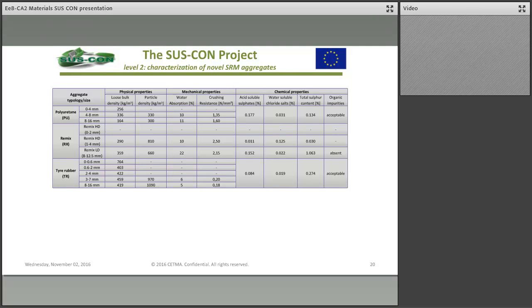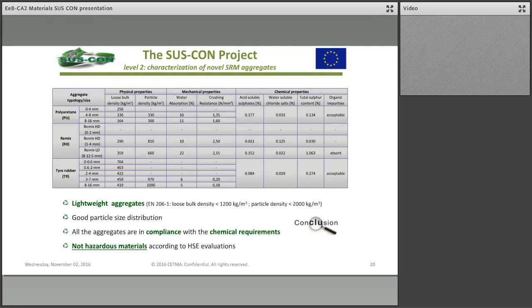This table summarizes the main results, but without going into too much detail. Each aggregate resulted as lightweight with a good particle density, that is essential for a good mix design. Aggregates from secondary raw material also resulted in compliance with chemical requirements and not hazardous in terms of HSE, and this also is a crucial point for a future use in a real application.